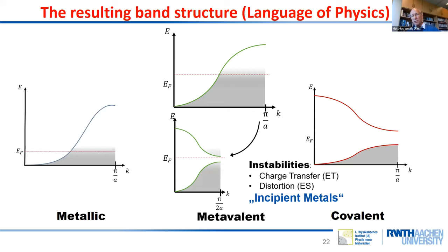There's either charge transfer, as described by electron transfer, our x-axis of the map, or there are distortions, as described by this concept of electron sharing. That's why we call these materials incipient metals. They're close to living their dream of being a metal, but they're not quite metals.